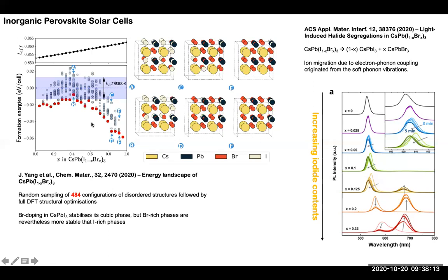oxide. Now, the other thing to think about is that as temperature rises, the whole phonon band structure renormalizes and the negative frequency disappears. So what you can do, I guess, is calculate a renormalized phonon density of states or phonon band structure and try to compare it back to your experimental data. But at the end, if you really want to say that the peak at that meV belongs to a particular mode, I guess you have to go to a high resolution.